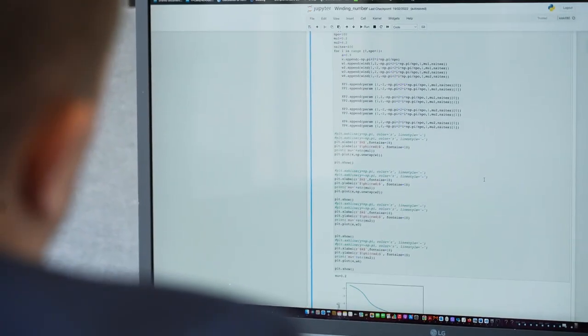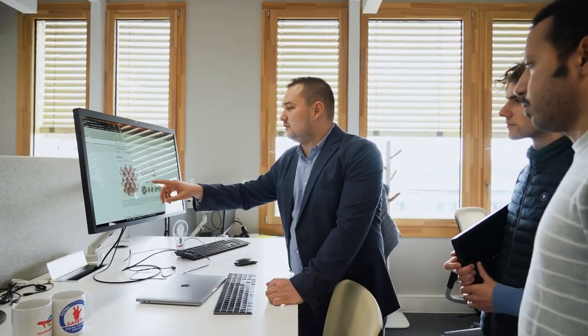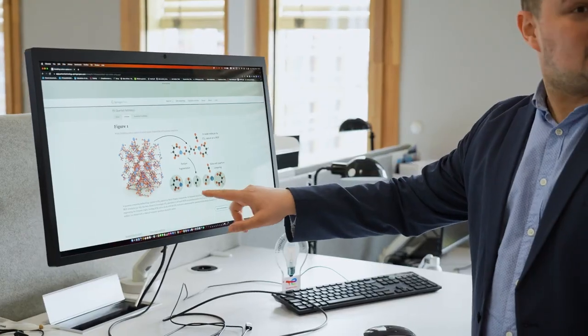Marco is able to determine really accurately some parameters. An important one, for example, is the point charge on each atom of the structures, which is absolutely key to determine water adsorption. This was really a key finding for us. We are able in some materials to use water to improve the CO2 capture.